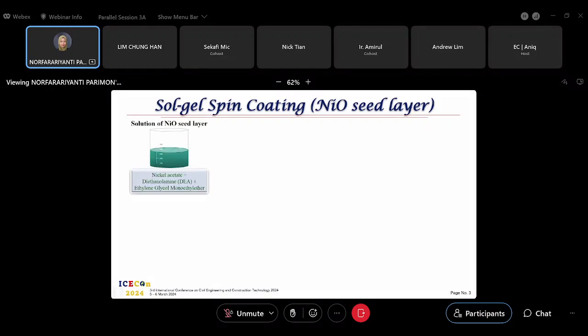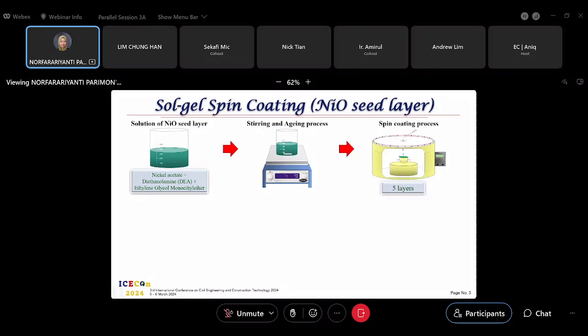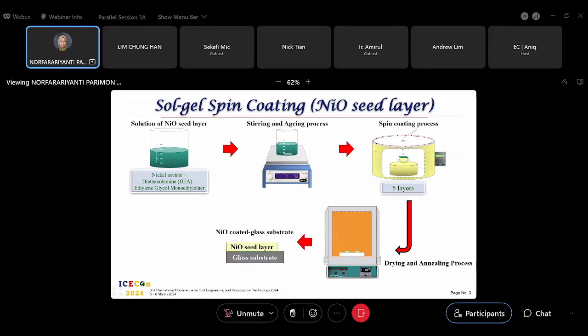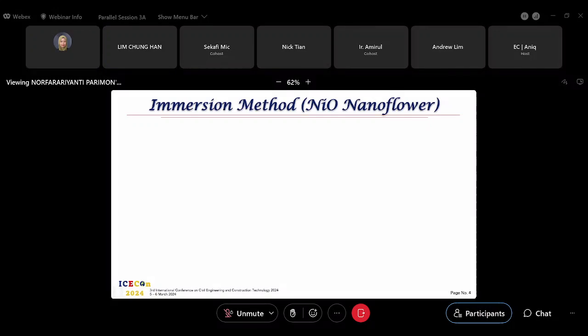The first step is sol-gel spin coating. We mix the solution using nickel acetate, diethanolamine, and ethylene glycol monoethyl ether, and then we start an aging process, go through the spin coating process for 5 layers, and then the annealing process in a common ambient environment. The nickel oxide seed layer, or thin film, will be formed on top of the glass substrate. Previously we used ITO, the indium tin oxide coated glass substrate, but this time we use the seed layer to improve the adhesion of the nanoflowers.